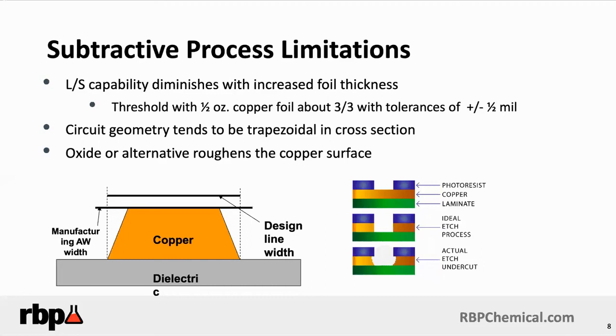Another situation we have to be very concerned with, which can exaggerate this, is poor resist adhesion. If the photoresist isn't adhering properly, the exposed resist is going to cause more undercut and more lateral etch from the etching process. Now, the etching process does play a significant role in this, and in a future Take 5 podcast, we'll delve more into the mechanics and the chemical aspects of etching. But for today, we want to focus on the surface preparation and adhesion for the photoresist.